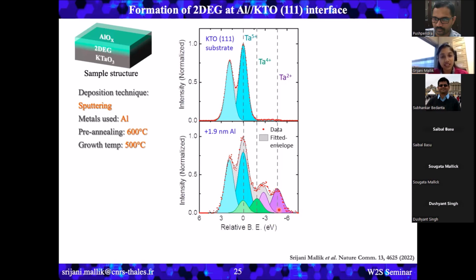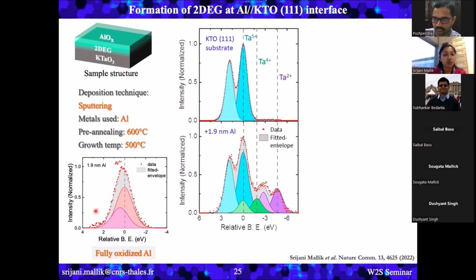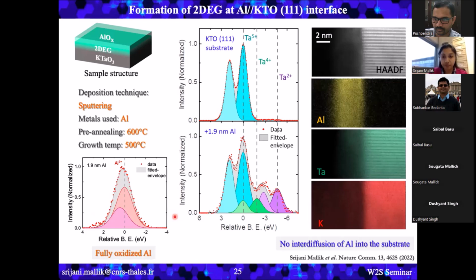Now, because this time we are talking about superconductivity, we have to be very careful, because aluminium is also superconducting. So we have to really check that in case we get superconductivity, it is not coming from aluminium, it's really coming from the KTaO3 2DEG. So we checked using XPS that the aluminium is 100% oxidized, so there is no metallic aluminium left. And then we also studied the cross-sectional TEM of this sample. From here, we can see that aluminium does not get interdiffused inside the substrate, so it is a quite sharp interface.